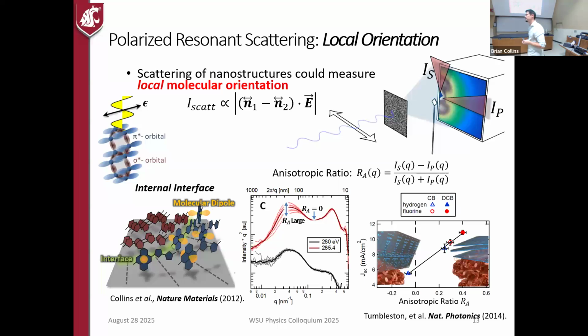Right. I can just clarify that what you're doing is with that polarized X-ray, you're exciting some molecular transition. Yep, which then scatters in these directions. Right, exactly. And the molecules themselves are random, but the fact that you're probing it. Well, in order to get this pattern, the molecules do have to have some pattern of orientation in a regular pattern. So think about when you rotate the sample, why wouldn't that do the same thing? Because the order has to be isotropic itself on the global scale. At the local scale, it's anisotropic.